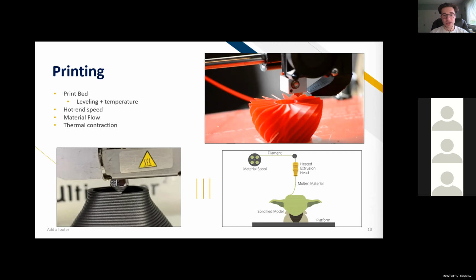Other things you need to be worried about are thermal contraction. So say if you like to print with ABS, you need an enclosed print area, so you don't have your temperatures changing. This would cause your part to crack and deform in certain areas, and that is obviously not what you want. We just have a few photos here of parts being actively printed.